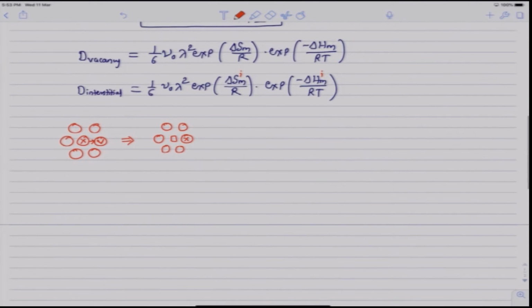because the next jump of the atom x is no more random, it depends upon the previous jump, and these are called correlated jumps. Now, the same vacancy can exchange with atom x multiple times, and such a sequence of jumps of an atom into the same vacancy again and again is called a correlation chain or a correlation sequence.